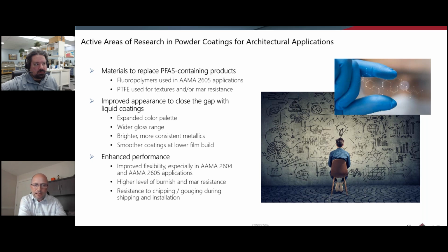The second bullet point, I talked a lot earlier, liquid versus powder on appearance. So on the powder coating area, there's always being iterative gains to close that gap in appearance. So expanding the color palette, making better metallics, smoother coatings at lower film builds, because you don't really need that high film build. You don't need 3 mils or 70 to 75 microns film build for any real reason other than to make sure that you're at least thick enough everywhere on the part and that the coating is smooth. So if you can get a smoother coating at lower film build, you would do that.